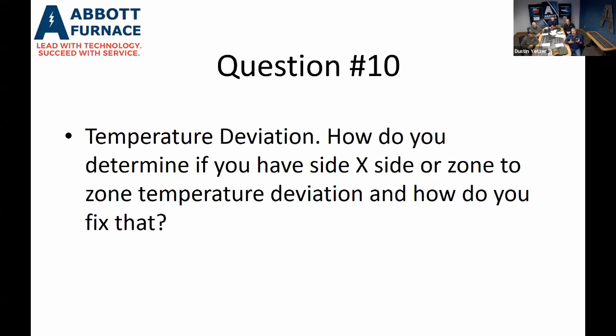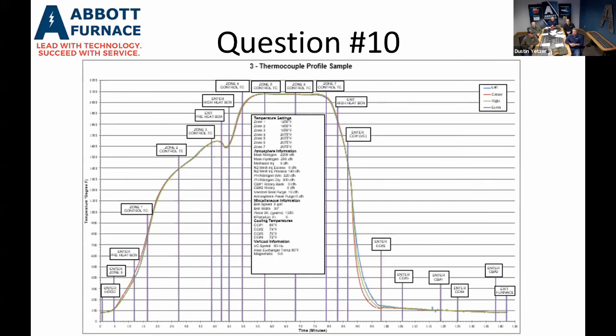Okay, so that's a two-part question. The first is side-by-side, and that is looking at the temperature inside the furnace, where the temperature profile would come into play. What we pulled up here is a typical 3 thermocouple profile that we would run on a furnace. We put thermocouples on the left side of the belt, the center, and the right side, and we run these thermocouples the whole length of the furnace, taking temperature readings. That gives us a nice profile, or temperature uniformity survey, of what the furnace is seeing. This will determine if you have a side-to-side temperature deviation on your belt that your product would see.